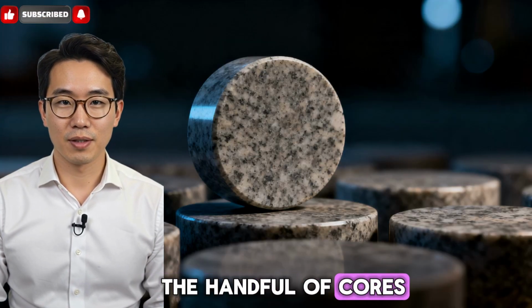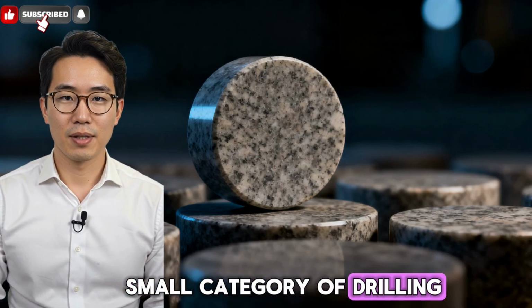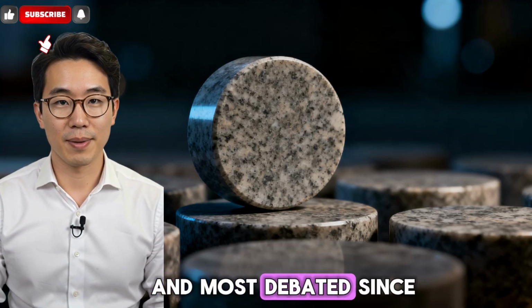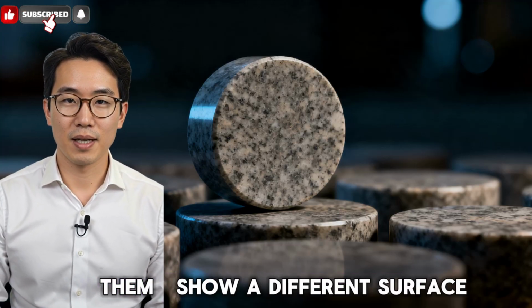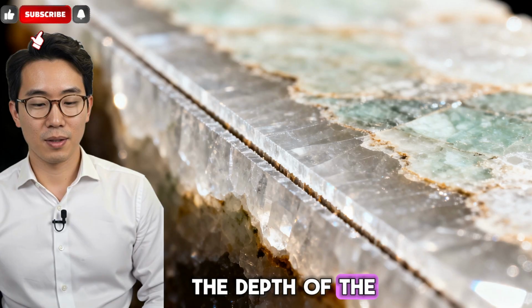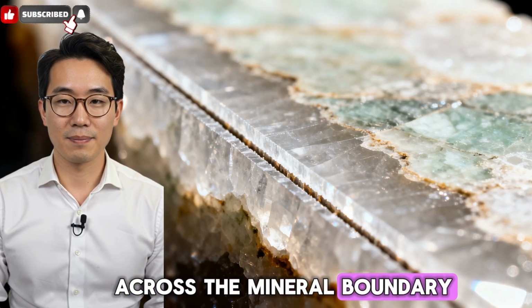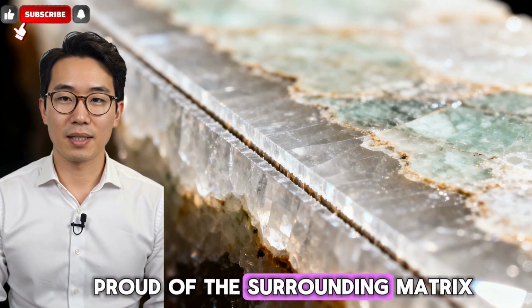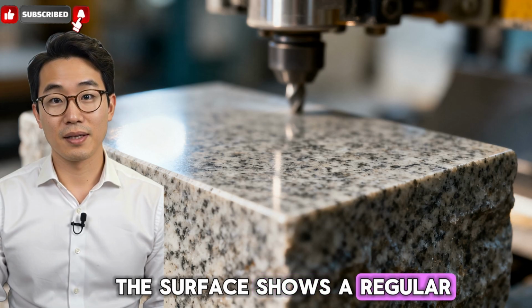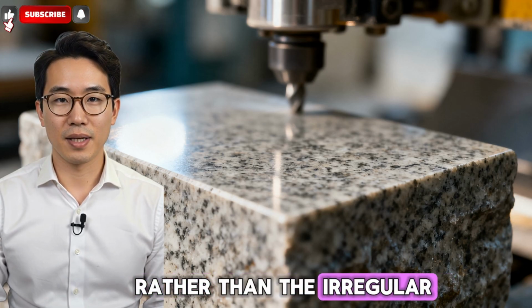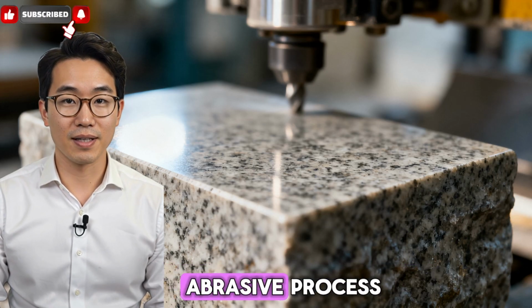The handful of cores, the specific small category of drilling evidence that has been most studied and most debated since Petrie first described them, show a different surface. The depth of the groove is consistent across the mineral boundary. The quartz crystals are not proud of the surrounding matrix. The surface shows a regular machined quality rather than the irregular mineral-following quality of the loose abrasive process.